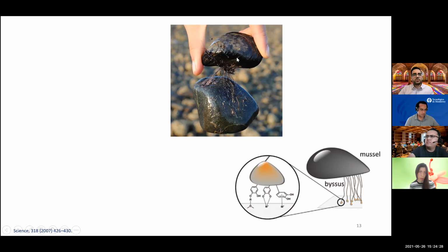Even those mussels can attach to adhesion-resistant polymers. For example, we have Teflon, polytetrafluoroethylene, known as a non-stick polymer. However, these mussels can interact with and attach to Teflon. The main thing is that there are some proteins secreted at the interface between the mussels and the substrate. The main hypothesis is that there are some amino acids in the structure of the proteins that have amine groups, and the other groups, as you can see here, are the phenolic groups.